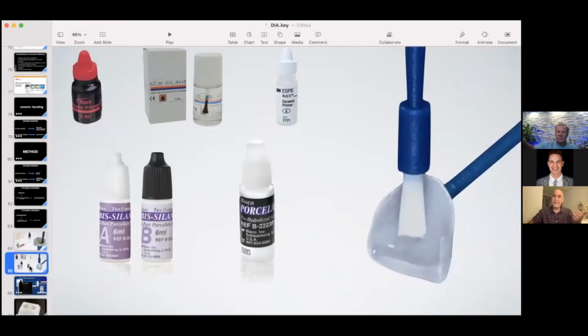Now your silane, you have 2-part, 1-part, single component, pure silane. That's what you need to get. Why? Because pure silane is hydrolyzed by the industry, by us, and then we provide it to you. Pure silane is stable in a single bottle, or you can have 2 bottles where you do your hydrolyzation in situ. A lot of people ask me, why should I have a 2-part silane? Well, if you're David Hornbrook, it's not a problem if you have a single bottle component, because you're going to be using it so fast, you're going to run out before it expires. However, if you're not doing that many restorations, having a 2-part silane can actually work for you, because every time you mix it, it's fresh. So you don't have to worry about degradation of a single bottle silane.